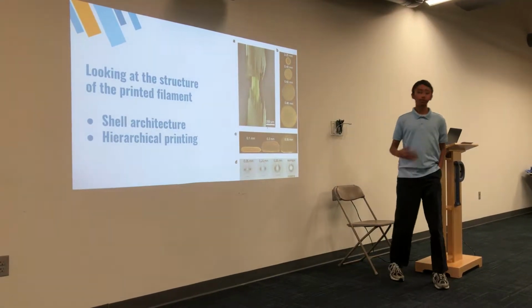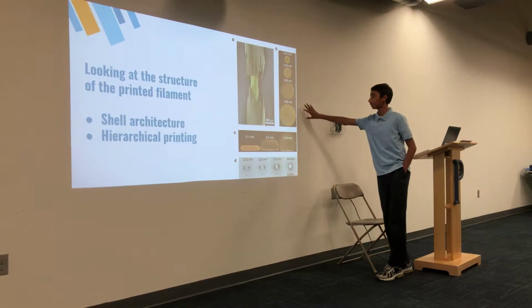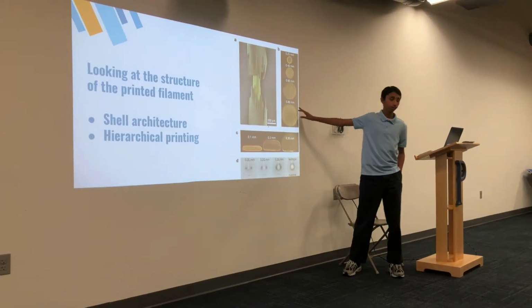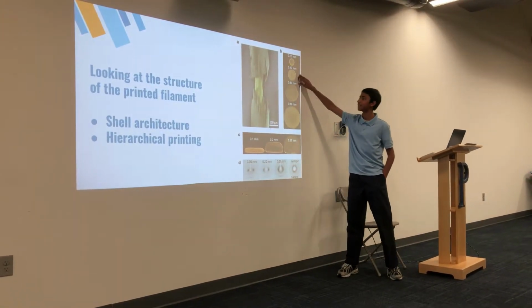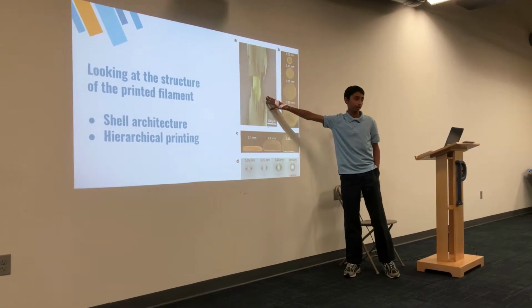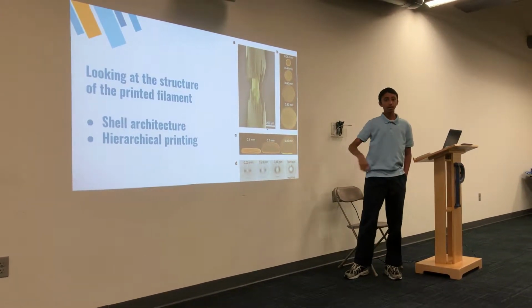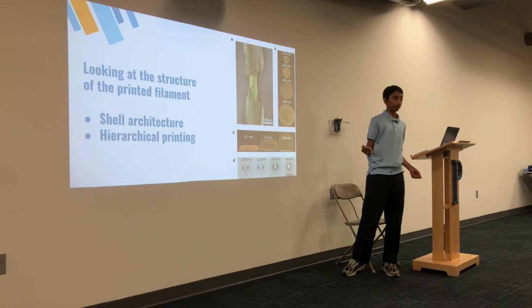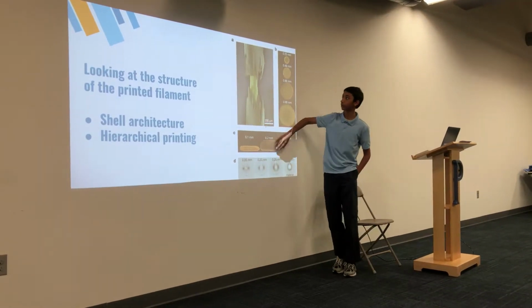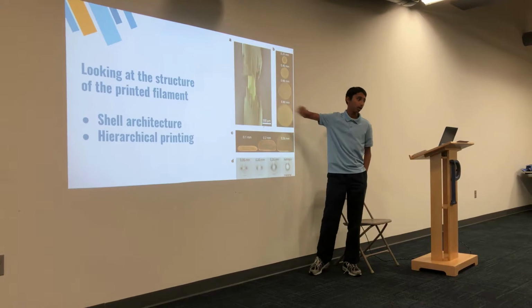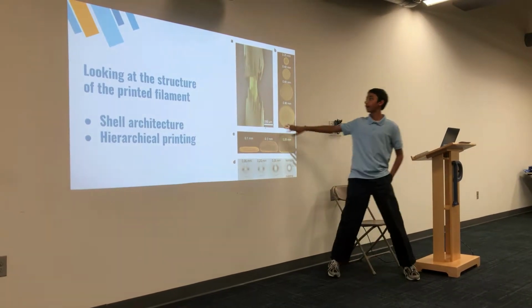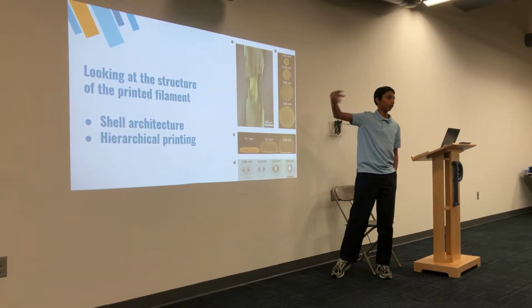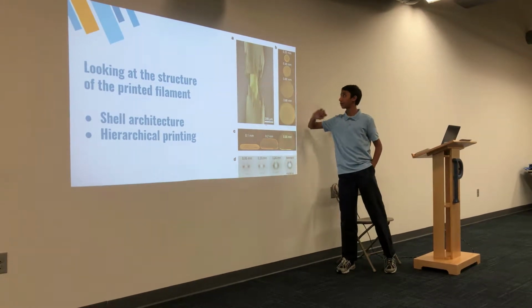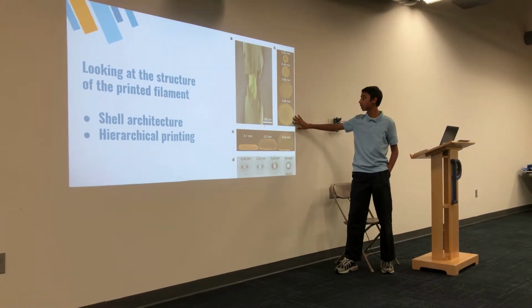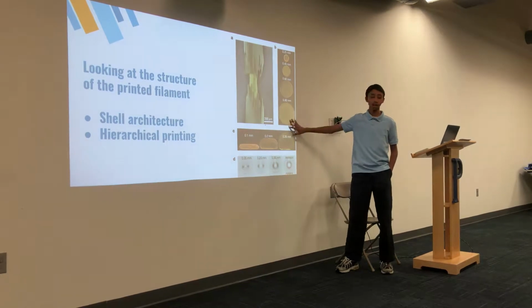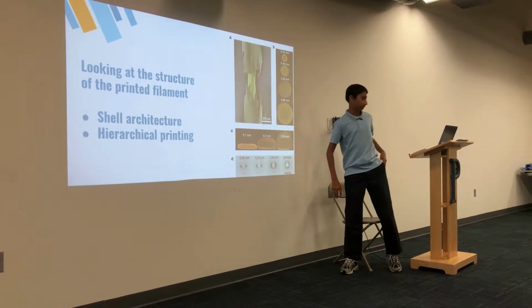So this is what, again, we talked about hierarchical printing. This is what that means. So A, this is an actual picture. What they did is they printed some of the filament and then they tried to rip it apart. And using a scanning electron microscope, you can see this kind of shell architecture there, where you have this inner filament, and then around it you have kind of an outer casing. And even if you look at the cross sections, you can see this inner filament and an outer casing, even in the layer height.